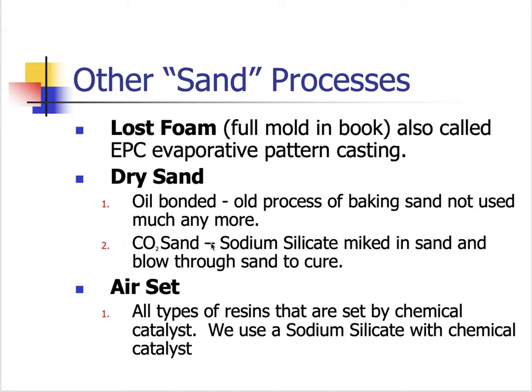and because you had to bond these things with CO2 or something like that, they came up with something called AirSet, which doesn't need any external catalyst like carbon dioxide. You can use resins that have a chemical catalyst. And so what you do is you mix them together, and you get a certain amount of time to work with them, just like epoxy or fiberglass, and then they cure and form a mold that's very hard, almost like a rock. And those we can use for either cores that go in a casting, or we can make the whole mold out of it. Okay.